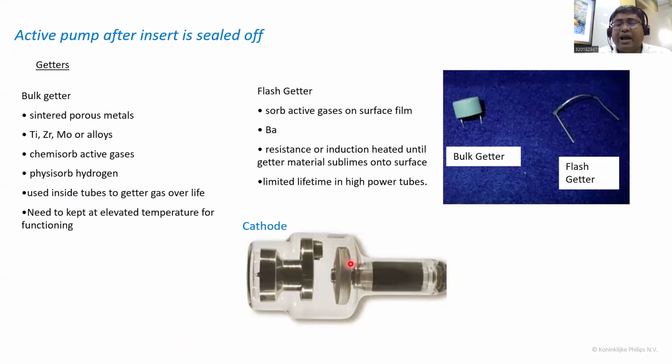It can go as high as 600, 700, 800 degrees centigrade inside. And it tends to dissolve the gases again, because we heat it, it starts emitting the gases and it loses the vacuum. So there is a second level of design.